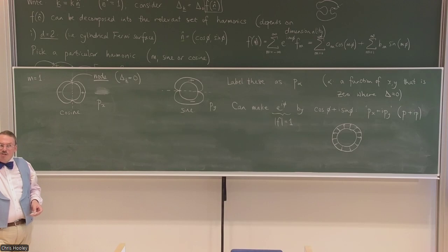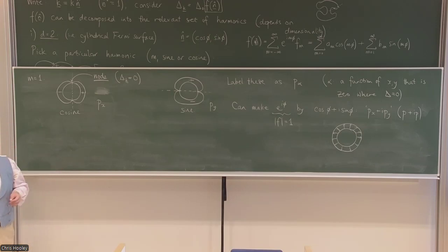So one case will be under strain. If you started off with a cubic material or a square material that had these superconducting states, you'd expect px and py to be degenerate in the fourfold rotationally symmetric case, but then if you strained it and broke that down to C2, it should start preferring one over the other.